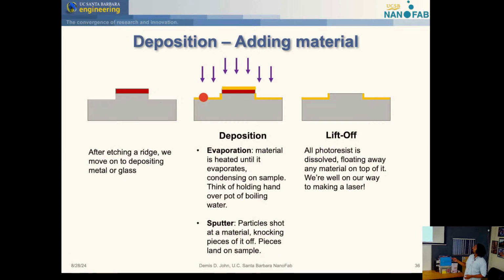So let's say I coated my wafer everywhere in metal, and I still have my resist here that dissolves in, remember what it dissolves in? Acetone, right? Nail polish remover. If I dissolve that, it will lift off the metal that's on top of the resist, and you'll literally see little flakes of metal floating around in your acetone beaker. It looks kind of messy, but once you clean it all off, we use rubbing alcohol a lot, isopropyl alcohol, you'll see these beautiful metal patterns on your wafer wherever there was no resist protecting the substrate. That's a lift-off process. There's other ways as well.